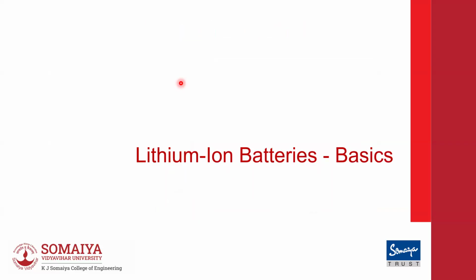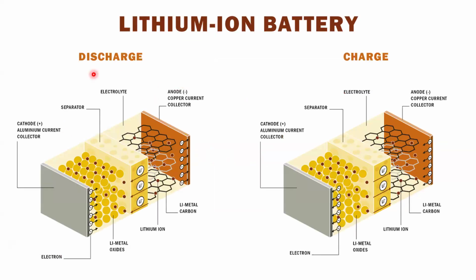Now some basics. I'm not going to dwell too much on the basics because this is meant to be more of an awareness talk. As mentioned, I have a lithium ion battery. I have an aluminum foil and a copper foil. The copper foil will have graphite on it. The aluminum will have my lithium compound on it, or lithium salt, or sometimes lithium oxide. In between, I have a separator, which is majorly a PVDF, PP sort of polymer. And what you see over here, the small dark spots are my lithium. The lithium basically moves in and out through the separator. Once it goes in and sets in between the graphite hexagonal layers, you basically have charging, and as it gets consumed, you will see that the lithium moves in the reverse direction.